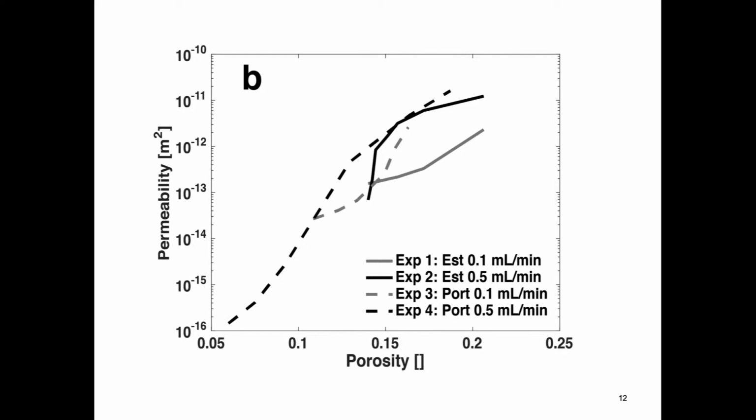Permeability was calculated directly on the segmented images using the Navier-Stokes solver that computes voxel-centered velocities. The permeability was found from the ratio between the total flow rate across the whole sample to the average pressure gradient multiplied by fluid viscosity, from Darcy's law.